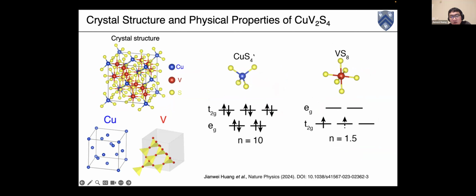If you look at their valence configurations, the copper atoms are completely filled with 10 electrons, and the vanadium atoms from this pyrochlore sublattice have an average of 1.5 electrons filling the 3d orbitals. So the vanadium bands can really feel this strong electron correlation effect induced by the Hund's coupling and the Coulomb interactions.